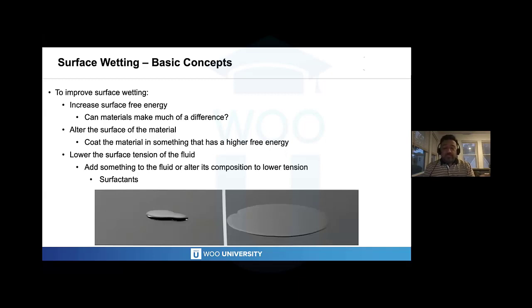We can alter the surface of the material. We can put a coating on the material that can lower the surface tension and create a situation where the water or whatever liquid can spread more readily because we've created a different surface energy to that material, to that surface. So that's something that we can also do. We can clean a lens material really well because a cleaner material, a more homogeneous surface, will allow liquid to spread more readily than one that has got deposits and things that create an irregular surface.